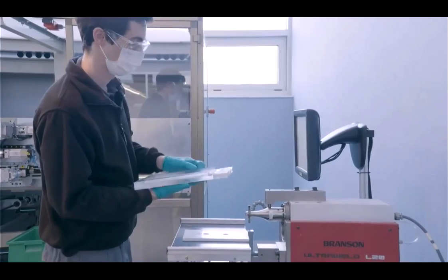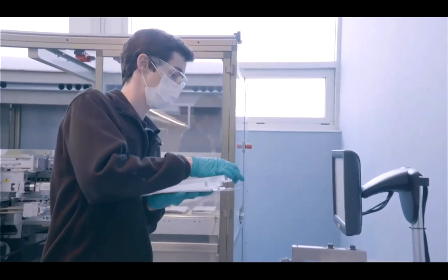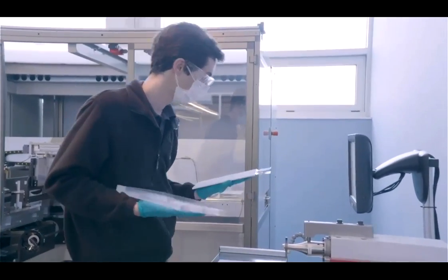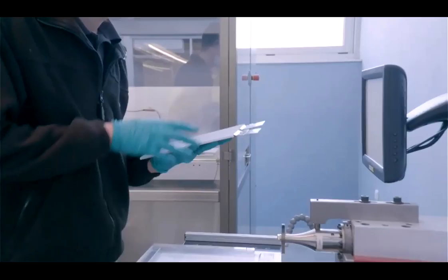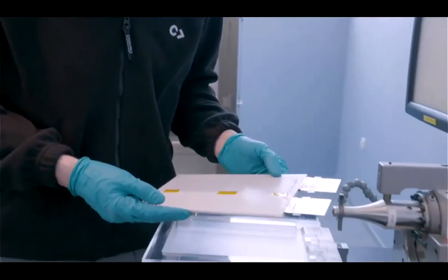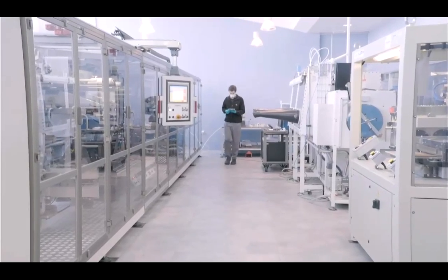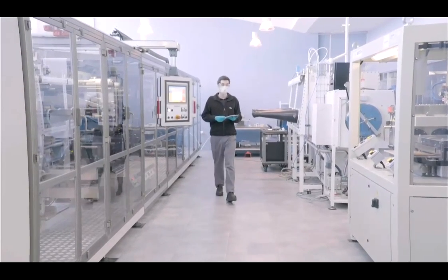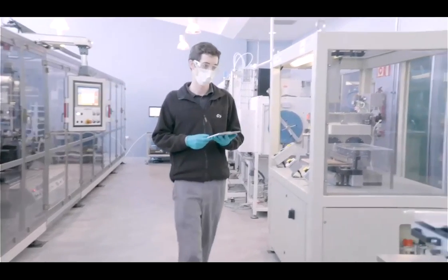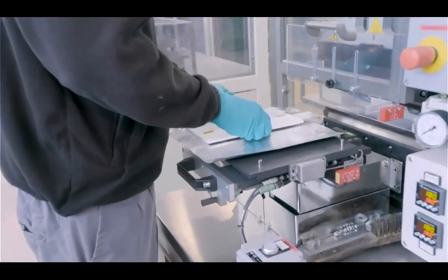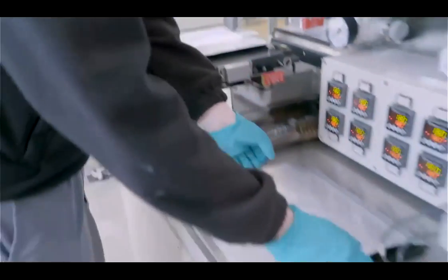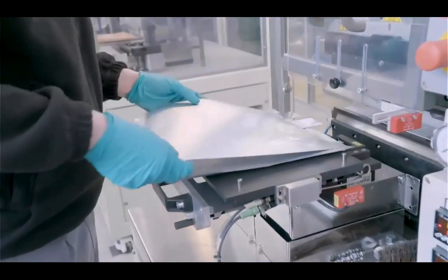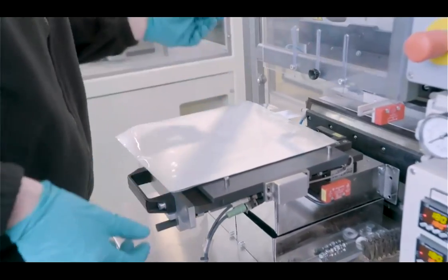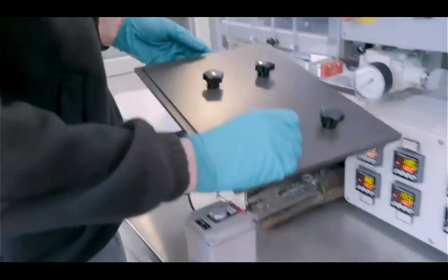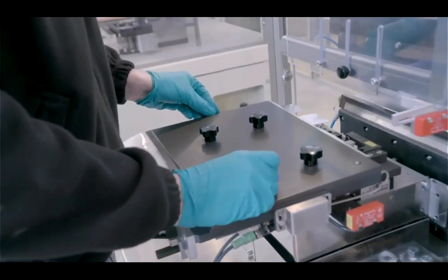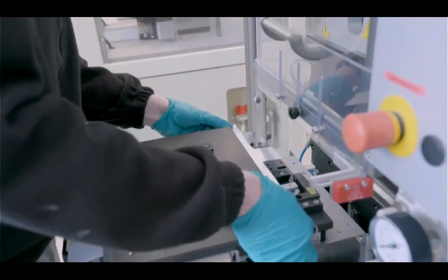Okay, so once the welding process is finished, the next step is the introduction of the stack in the pouch foil. My colleague is positioning the stack in the pouch foil. This pouch foil has been deep drawn in an earlier process. The width of the deep drawn will depend on the stack, on the number of electrodes that we have in our stack.